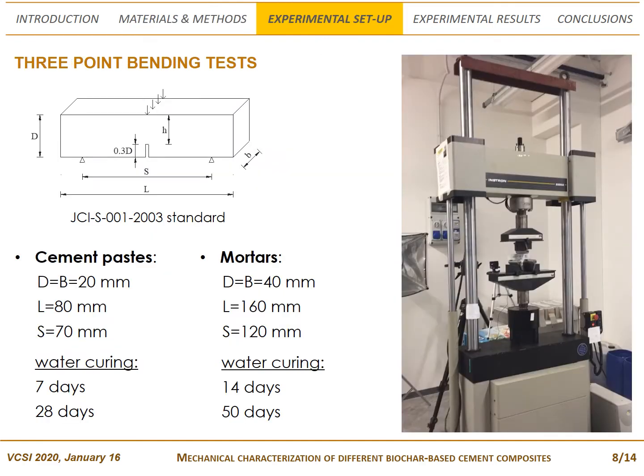All the experimental composites were cast in prismatic molds by using the geometry and the dimensions recommended in the Japanese Concrete Institute standard. Once the curing in water was finished, a U-shaped cut, 3 mm deep for cement pastes and double for mortars, was made in the middle of the specimens.